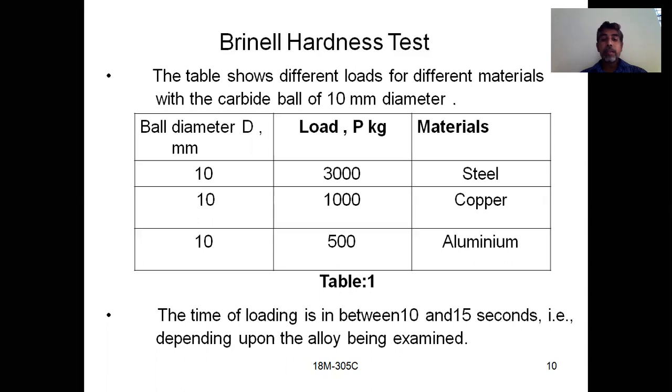The time taken is between 10 to 15 seconds depending on the alloy being examined. So how much time do we have to apply the load? When you apply the load, you have to keep it for some time before releasing. That means you have to keep the load in action for 10 to 15 seconds.